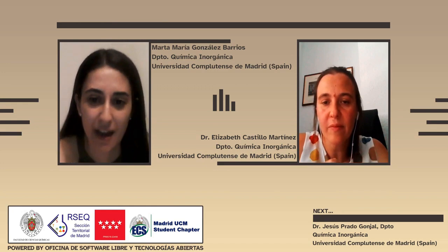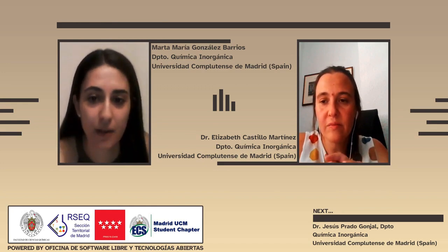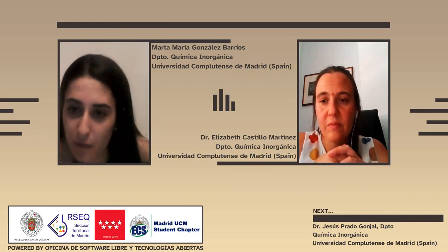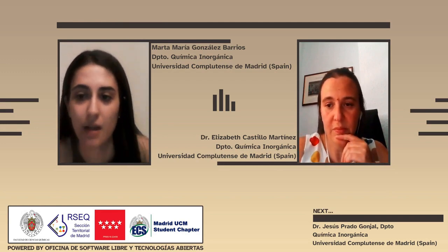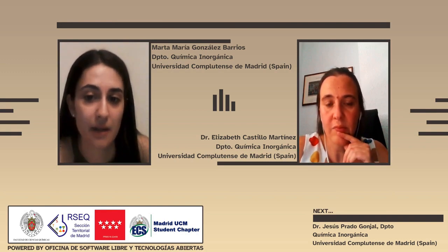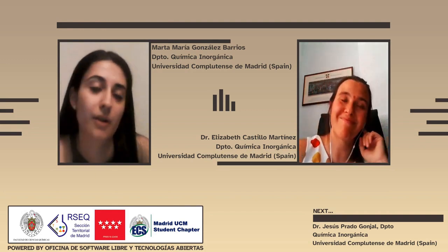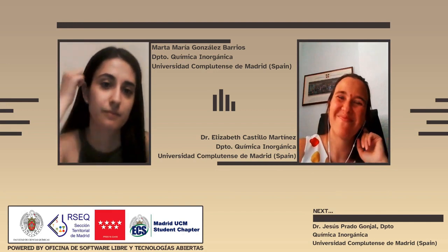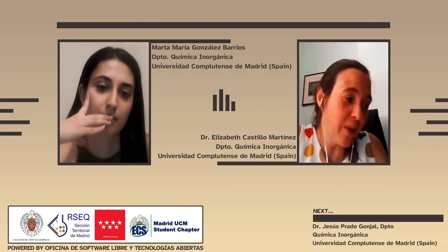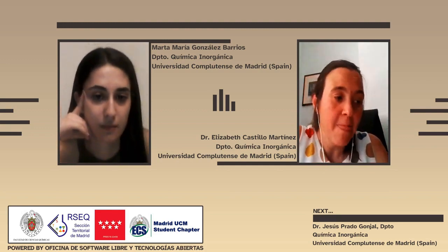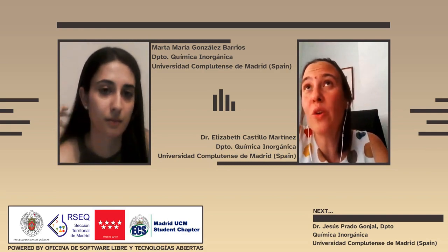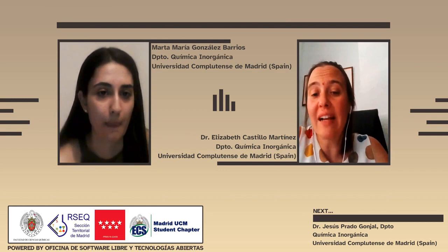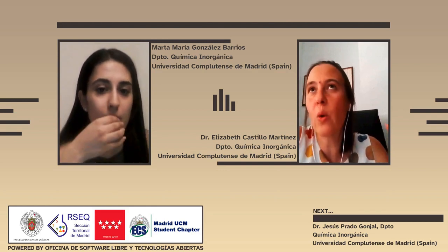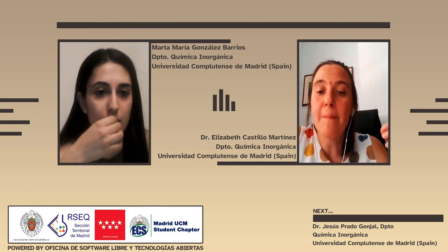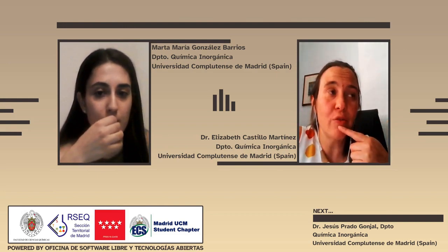Thank you so much, Elizabeth. Another question from Cynthia Redondo. For measurements in a laboratory, do you consider that alkaline metals as reference electrodes are reliable, or can there be other alternatives? Well, this is actually one of the issues with highly reactive alkaline metals. As you go down from lithium to sodium to potassium, reactivity increases, and actually lithium metal is quite a good reference electrode, but sodium metal does not show to be a very good reference electrode.